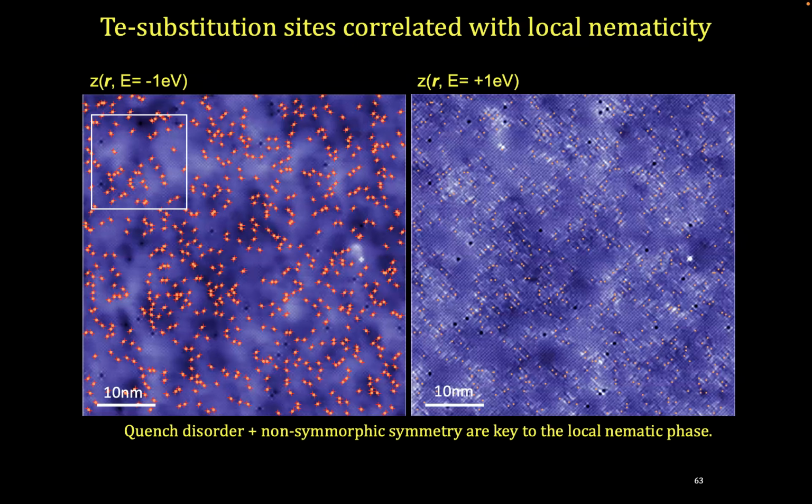And then we can further correlate, and indeed we can identify all the impurities in the system. So this is only 2% though. If you look carefully, most of these, when you have more doping atoms, you can see more patches of these one dimensional features. But when you have less doping, then it becomes clear: just an atomic lattice, a cleaner surface.